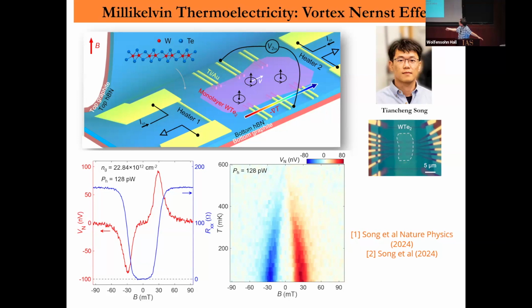The fact that it goes back to zero tells us we don't need to worry about the Nernst effect coming from electrons or holes, because if they were there, the signal should be finite here—it would be a linear line like this, since it's a transverse Nernst effect. We don't see any of that, so it's negligible compared to the Nernst signal arising from the vortex; that quasi-particle signal is very small, so we don't worry about it in any of my presentations.